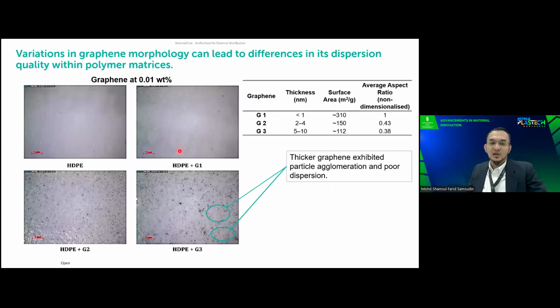And this is one of the examples where we characterize the dispersion of graphene at 0.01 weight%, where we study different types of graphene. We label them as G1, G2, G3, where G1 is very fine in terms of the morphology and size, and G3 is a bit coarser. And this is what we see after we do the melt blending and make it into a thin film at around 250 micron. Then from the microscope, we can see the dispersion of graphene.